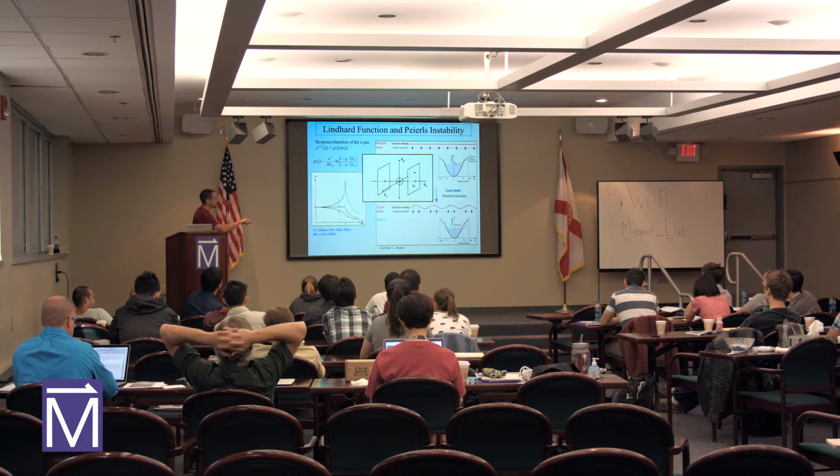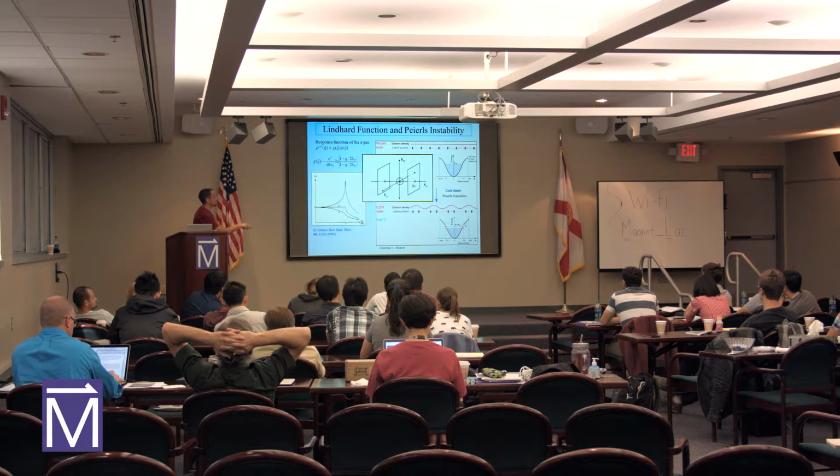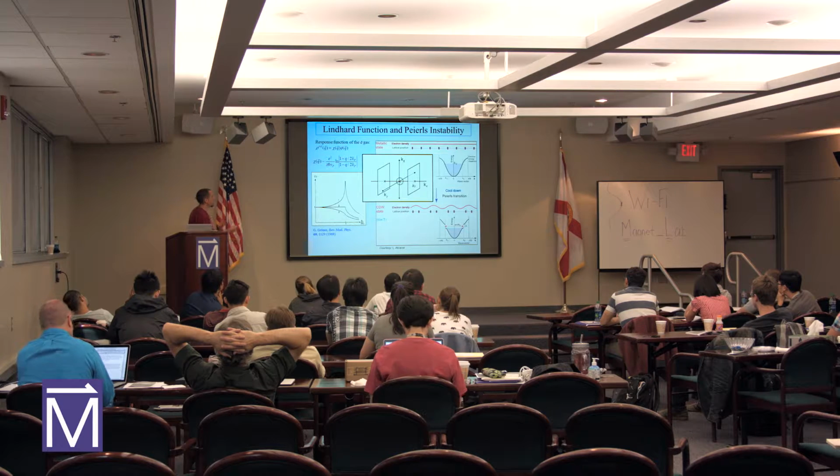Because there are new positions in the lattice, the electron density changes and forms around these new lattice sites. So there's a charge density that has a periodicity, so it's a charge density wave. And when something forms a charge density wave, because a gap opens up at the Fermi level, it becomes an insulator. This isn't just some theoretical idea. We, of course, can measure this in real samples.